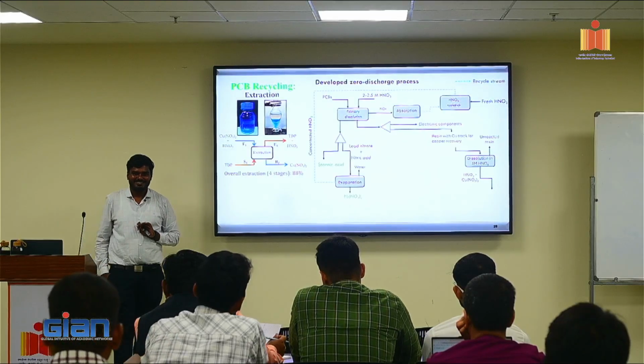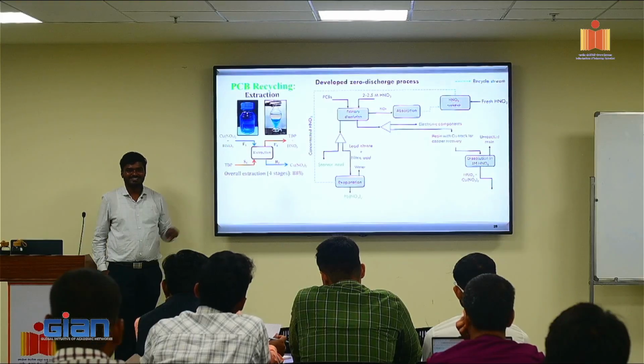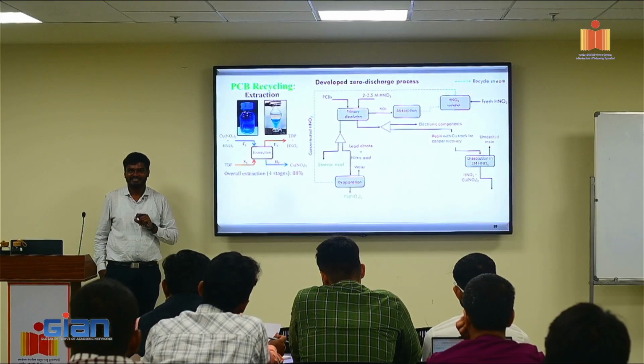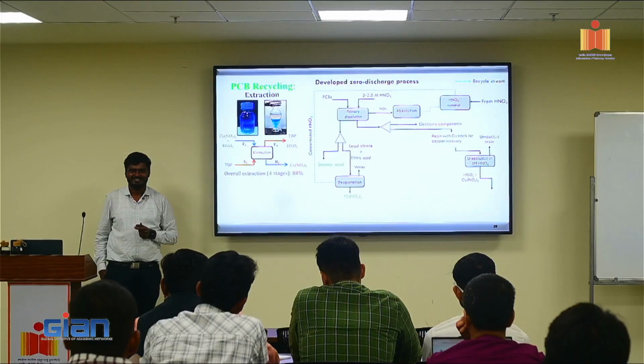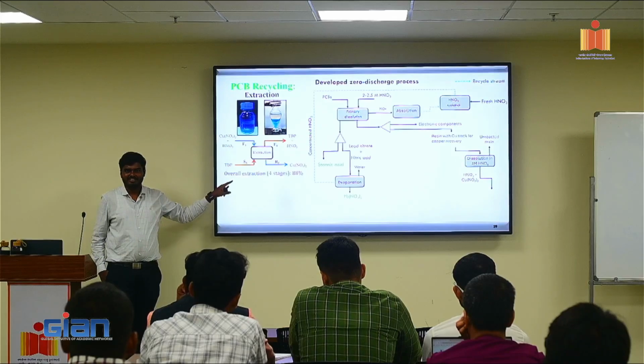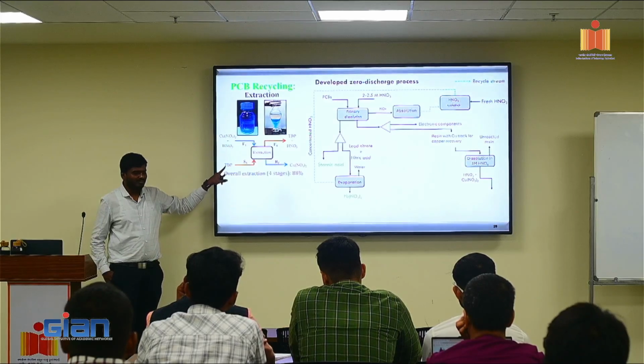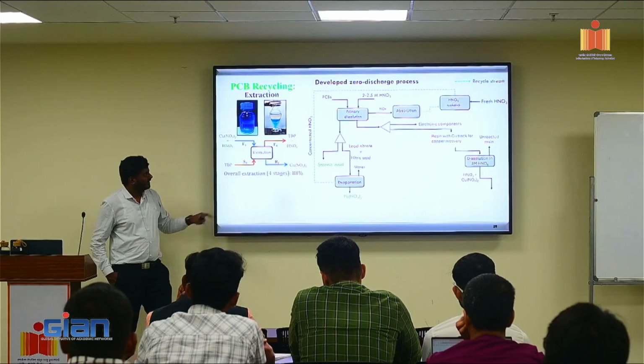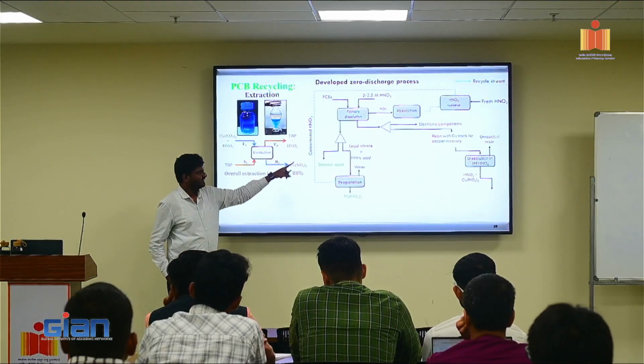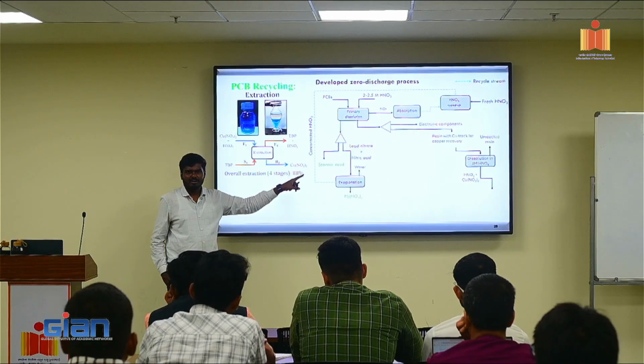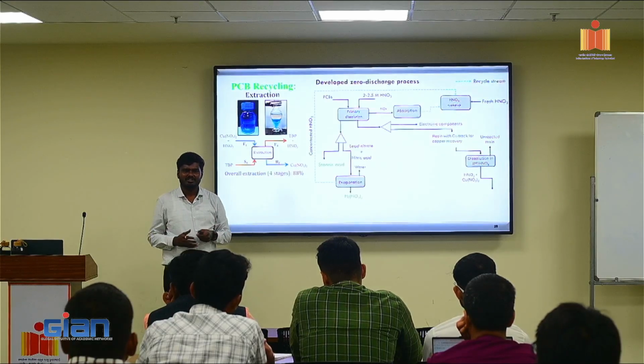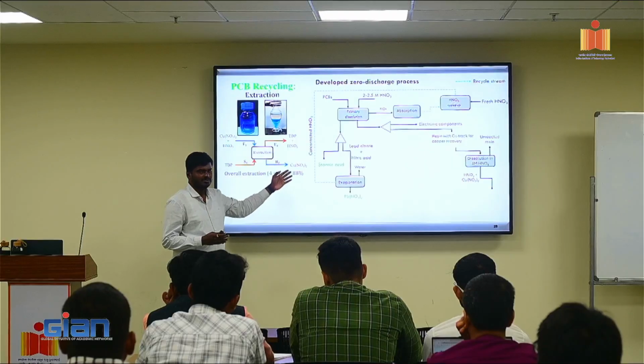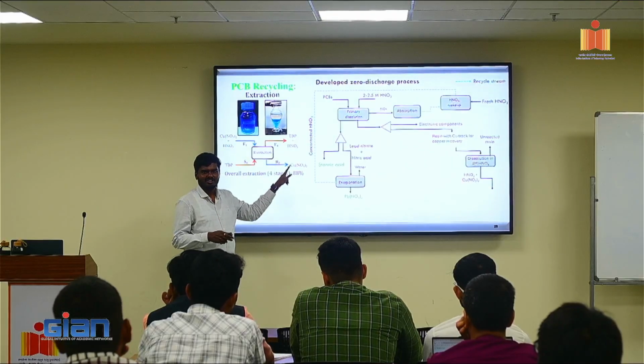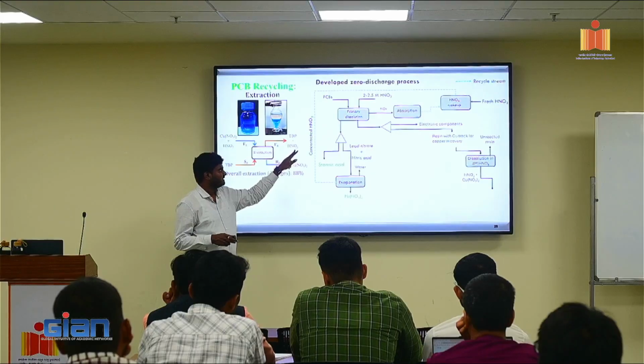So now I thought, can I modify this? So what we did, we modified this by adding kerosene. Kerosene is cheap, right? So 70% TBP plus 30% kerosene was giving the same results. So later we modified this and we were using it. So now you have the stream of TBP plus HNO3 and you have copper nitrate. Now you can do electrodeposition and you can recover copper as it is, because you don't need to dilute, as you have already separated the nitric acid.